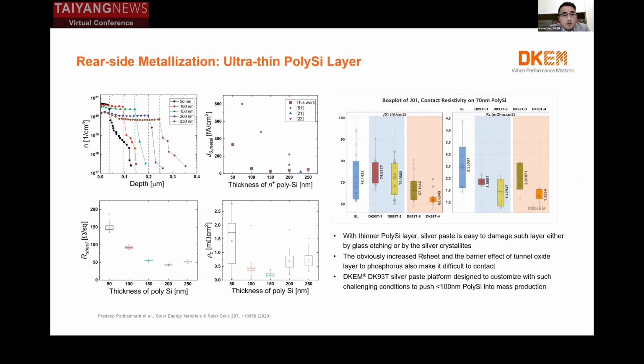So for DKEM, we developed our paste and modified it. We made a lot of effort, in about two phases. In phase one, we reduced the contact resistivity easily, but the J0,metal was still very high. Then we modified further and achieved quite low contact resistivity, and at the same time very low J0,metal. So that means the DK93T platform is actually designed to be customized for such challenging conditions. We are confident to push less than 100 nanometer polysilicon layers into mass production.